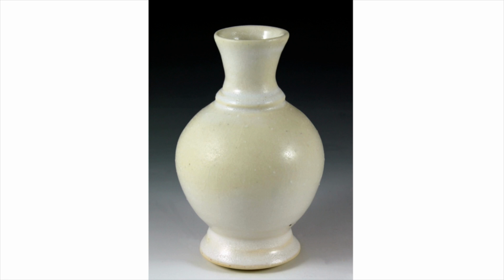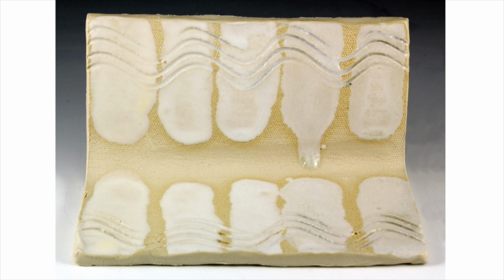Now, to lower the melting temperature of a glaze, you may want to just add a frit, like frit 3124, to the glaze in 5 to 10% increments. Frits are industrially made flux ingredients that behave like low melting feldspars. So adding a frit sometimes eliminates the particular surface quality and color influences that are often produced by certain fluxes, like strontium and barium.